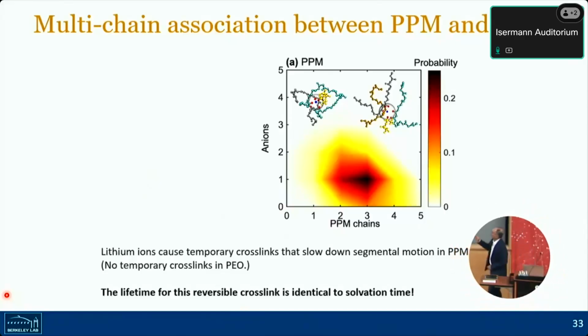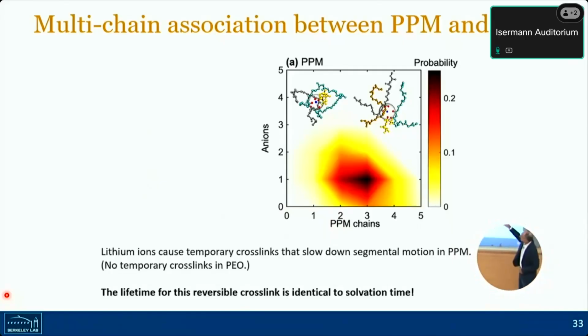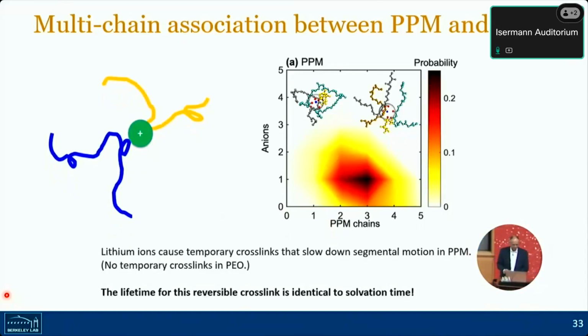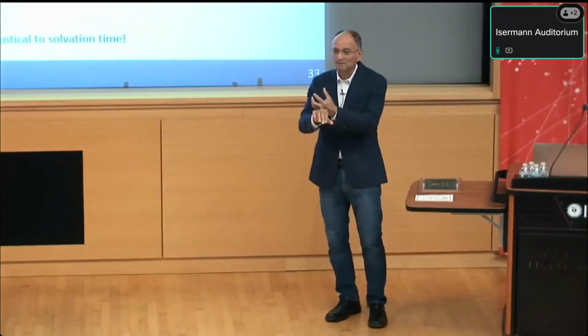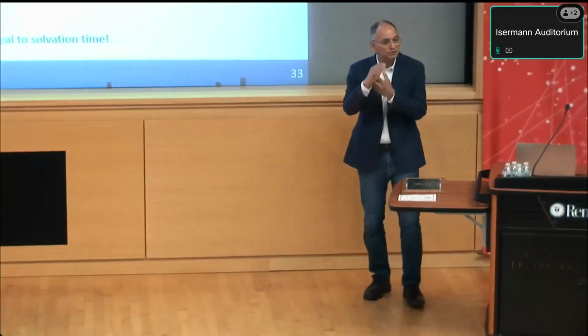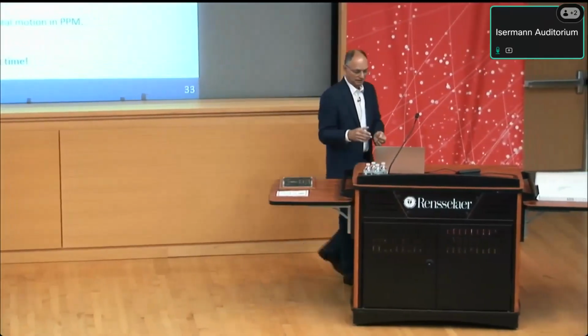On the other hand, you see a plethora of 2 and 3 chain conformations with 1 or 2 anions. That's not the important point. The point is the number of chains is more than 1. And so the solvation structure looks like that. And you see, when 2 chains are stuck together, it becomes a different polymer. It becomes a cross-linked polymer. Okay? And so this new feature that I saw in the quasi-elastic neutron scattering, I argue, is because of the fact that you have a temporary network, which you never found in the case of the other electrolyte.